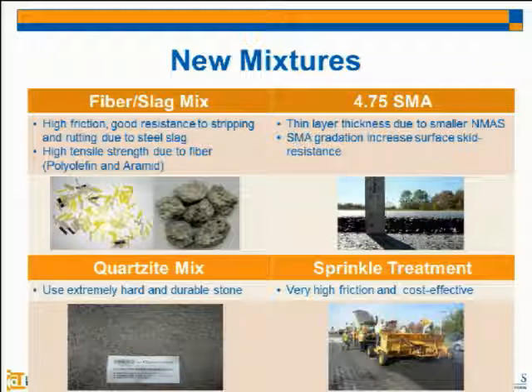The fourth one, sprinkle treatment. This was actually used a long time ago in Illinois and Georgia, but recently people haven't used this mixture or treatment that much. The main idea is we use a regular, cheap base asphalt mixture. But after we place these materials in the field, before we compact, we spread very coarse aggregate on top, and then compact. So it's like a chocolate chip cookie. We just spread the very strong coarse aggregate on top, and then compact. This will increase the friction on the surface.